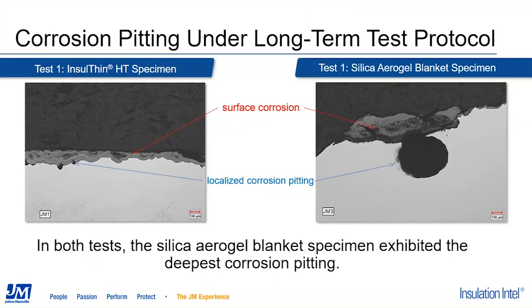So we look at the sample on the right. This is going to be the silica aerogel specimen. Again, that white on the bottom is the actual pipe itself. The black at the top is going to be background noise. You can see the red line pointed to the surface corrosion. And then we can see that pit, and that pit extends further into the pipe specimen. Again, with this pitting corrosion, this is where you could actually have a failure with minimal overall thickness loss, wall thickness loss of the pipe.